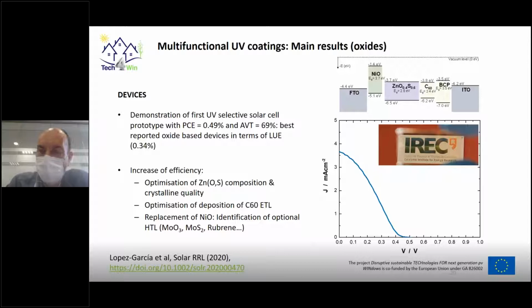What is also very interesting is the optical quality. Here you can see a photographic image of the solar cell just on top of the IREC logo, and as you can see, we cannot recognize the presence of the cell. So it is really a transparent solar cell without any coloring effect. In fact, this is one of the best reported oxide-based ultraviolet selective devices up to now in terms of what we call the light utilization efficiency, which is just the product of the photoconversion efficiency and the visible transparency. We are now working on the optimization of these first proof of concept devices to increase the efficiency essentially.